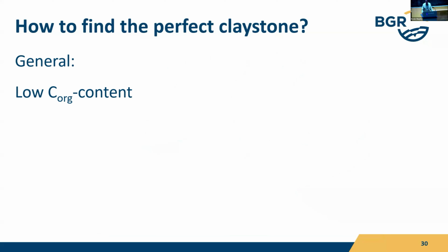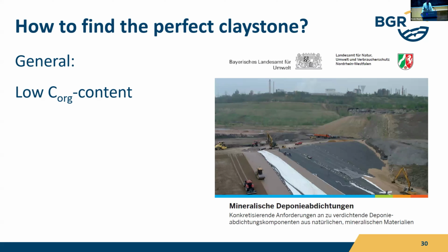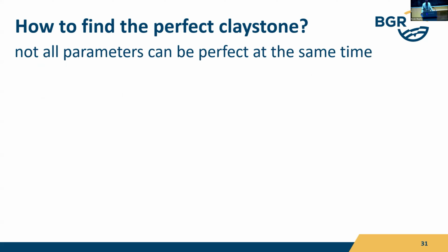Generally, and that is out of the question which road to take, the organic carbon content should be low, because there's not any parameter which is in favor of high organic carbon contents. You have formation of gas, you have microbial activity, you have the possibility to generate secondary porosity. So that is really an issue, and it's not really a secret, because if you look at the German legislation for building the barriers for landfills, then this parameter, the organic carbon content, is included, right? And if we even use it for our landfills, then it should be possible to consider this parameter for the maybe even more important barrier, the host rock as well.